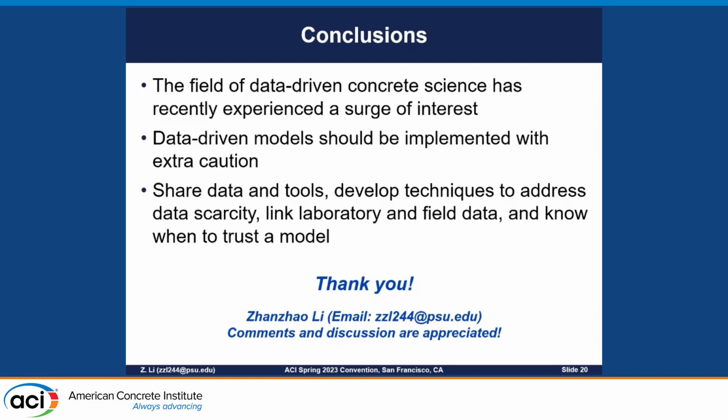In a recent analysis of over 20 years of papers that I did, almost half of them didn't report the cement type and strength class of the cement, or they didn't specify if the water content in the mixes was the effective or the total water. The second point that you very interestingly made was about the correlation between superplasticizer and water amounts. That is certainly a good point, and I would encourage everyone to keep that problem in mind. Concrete science is multicollinear. Every variable depends on the other variables in the mix, and we seem to forget that.